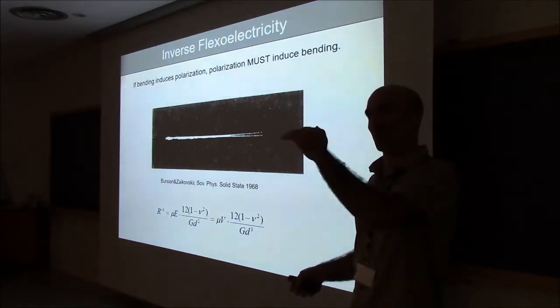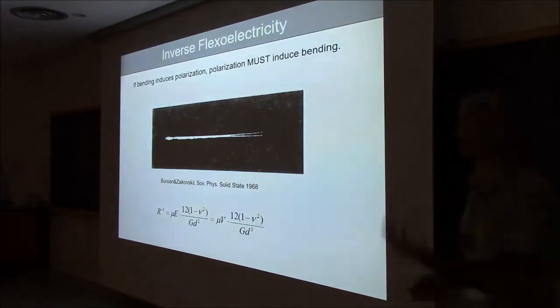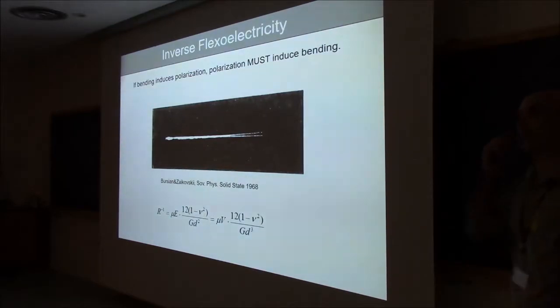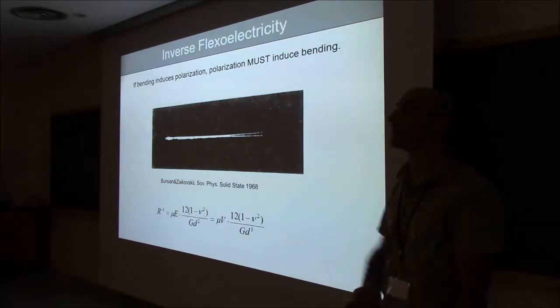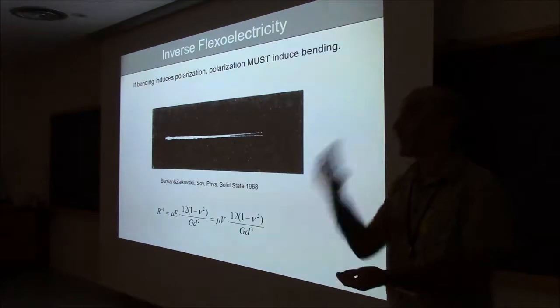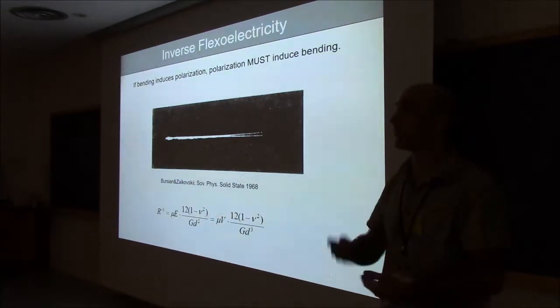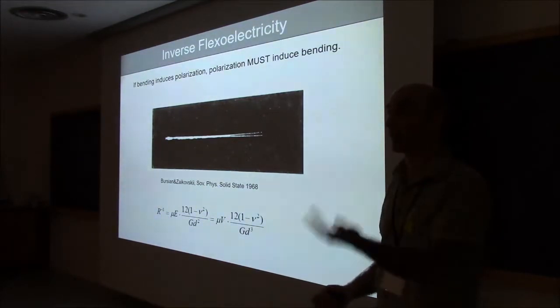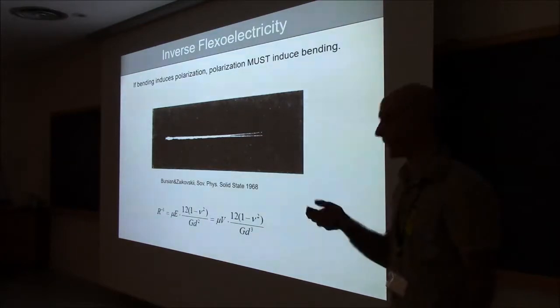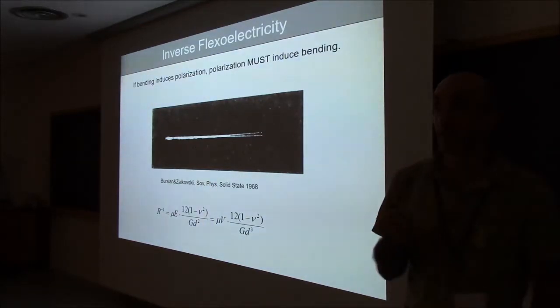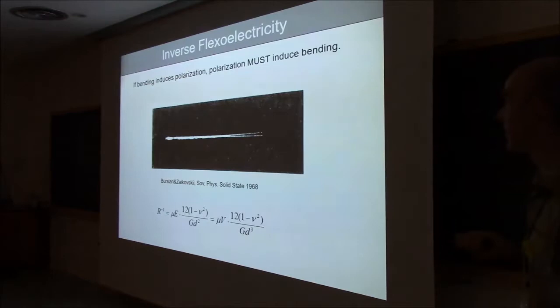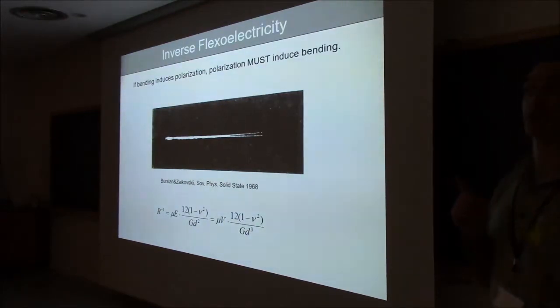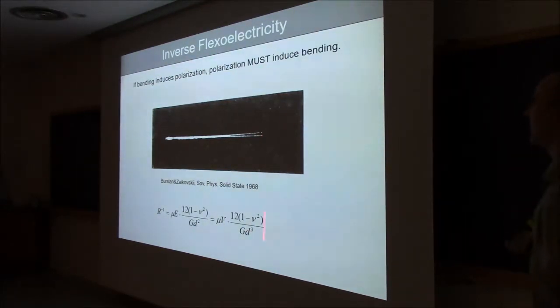It's difficult to see that, right? So you're not going to see it, and that's why people haven't seen it. But if you take the same strontium titanate and you make it 100 nanometers thick, then it will bend by several tens or even hundreds of nanometers, and you will be able to see it with the right equipment, of course. And interestingly enough, inverse flexoelectricity was the very first experimental demonstration of flexoelectricity. So inverse flexoelectricity was observed before direct flexoelectricity. And of course it was in the Soviet Union.